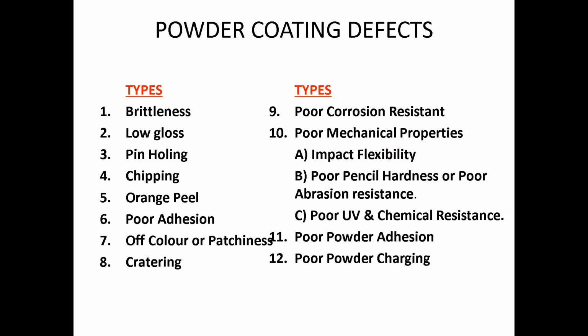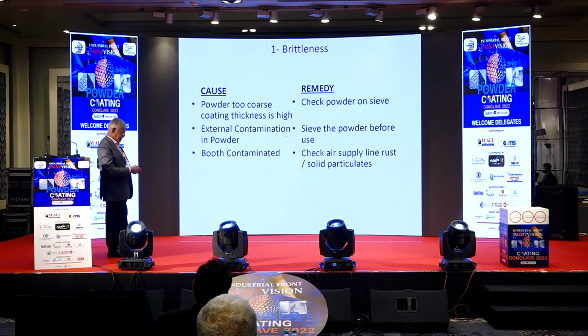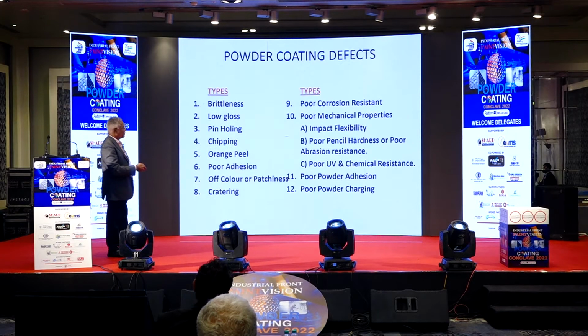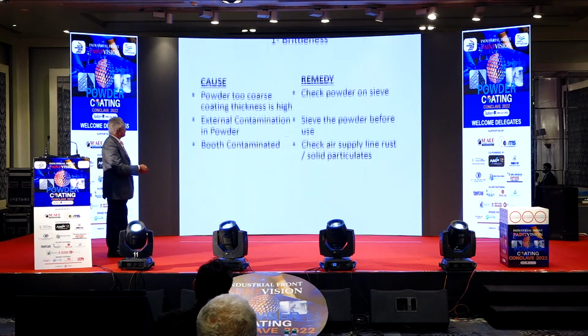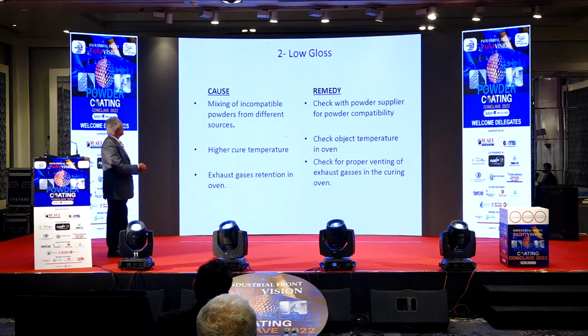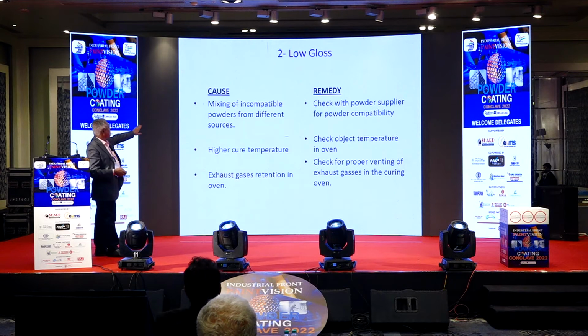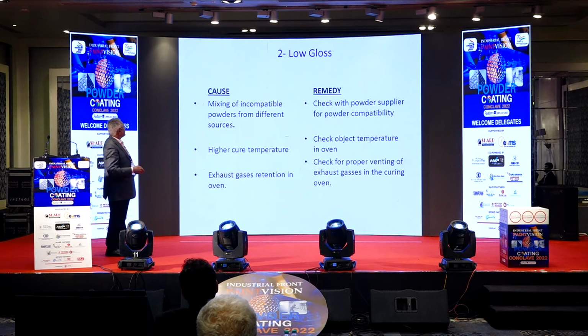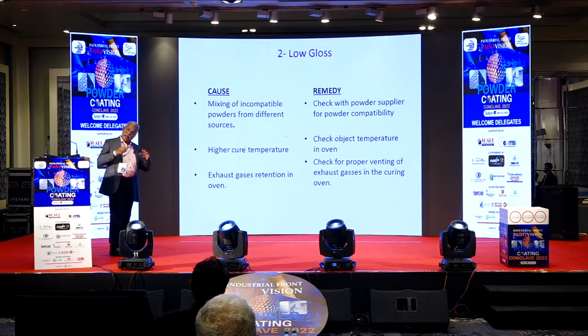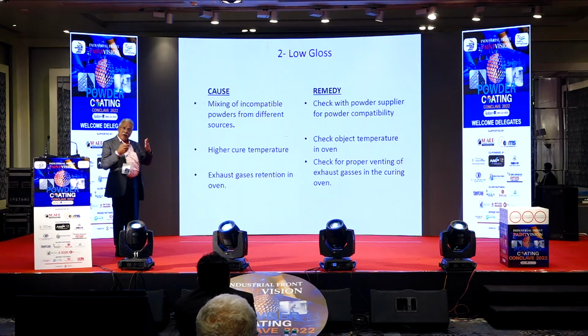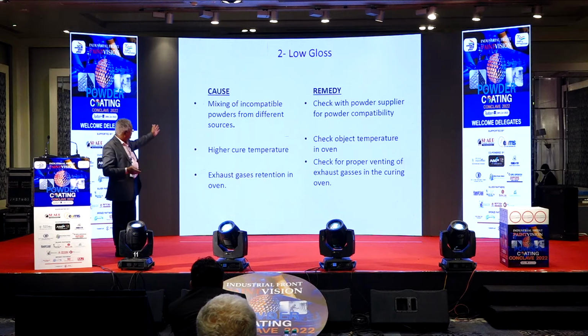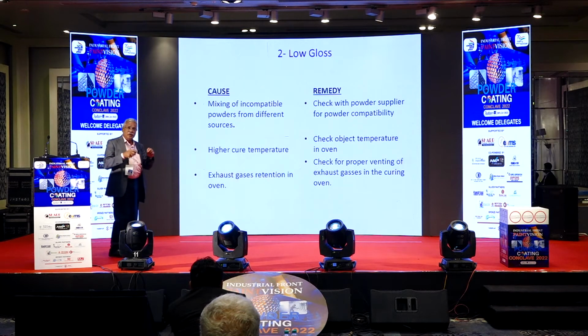Defects. A lot of defects we can find. Low gloss is due to mixing of incompatible powders. It will be a different company's powder, a different resin system's powder. Sometimes it will be incompatible, so you will not get full gloss. You will lose the sharpness. That is why you should not mix different companies' different grades of resin.